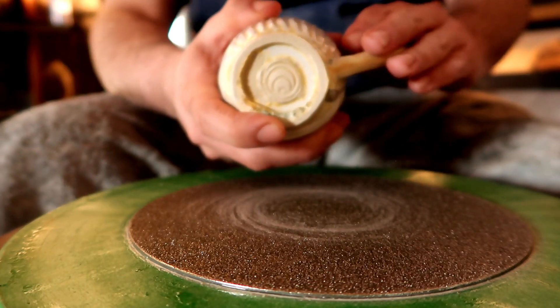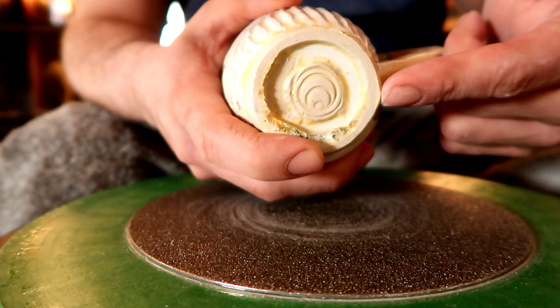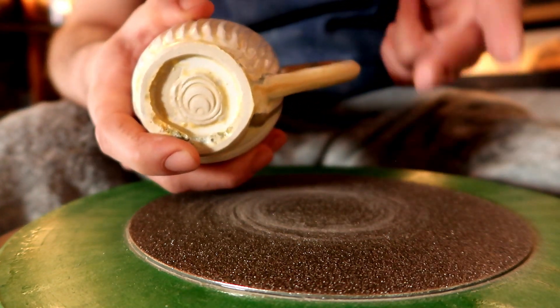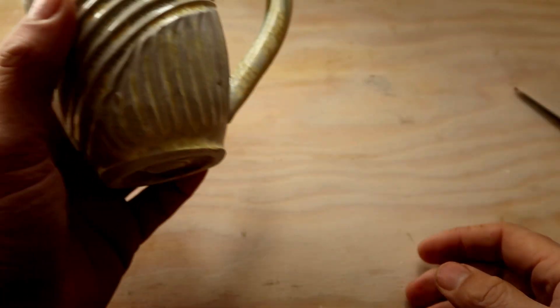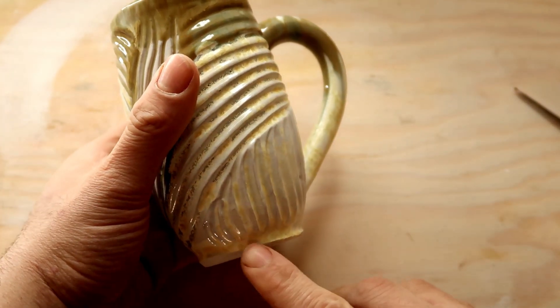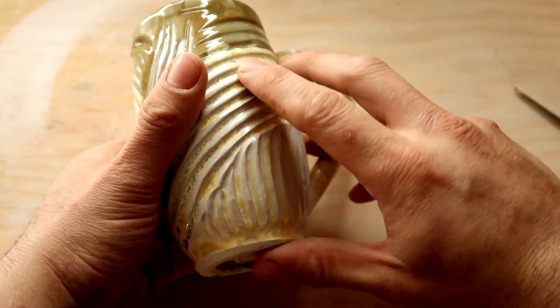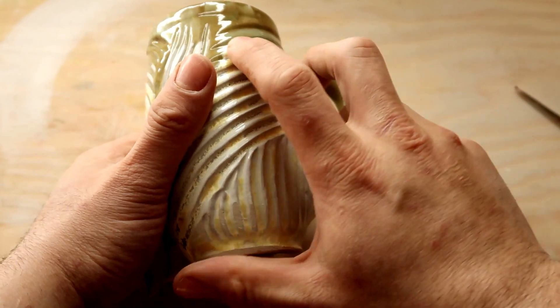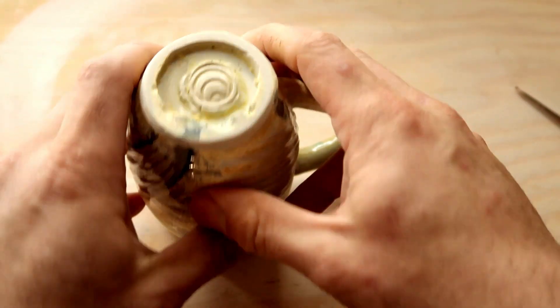All you really had to do was get a little bit of water, get yourself a sanding disc or at least a regular old sander, and just start grinding away. The key is that you want something relatively coarse, number one, and number two, you want to put as little energy as you can into it — simply let it spin on your wheel. As a final step, you can probably see that this pot is almost pretty recovered. The glaze flange is no longer there, it's nice and smooth, it no longer has the ability to cut us. This is pretty good — I would say this pot is saved. But if you want to get a little more intricate and you notice there's a little bit of glaze on the inner ring of your pot, there's a very easy way to save that as well.